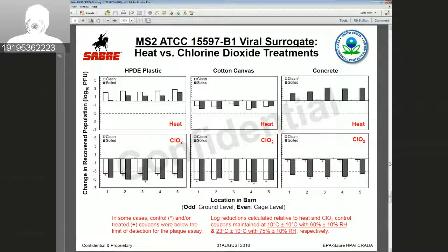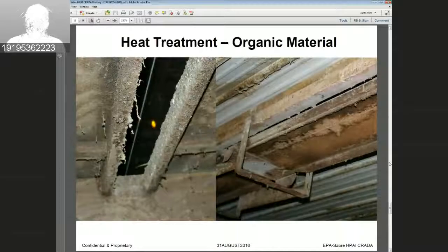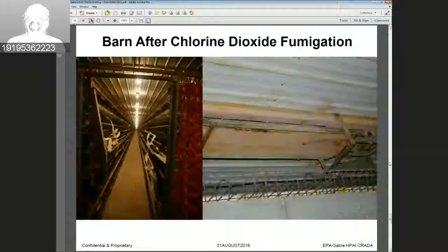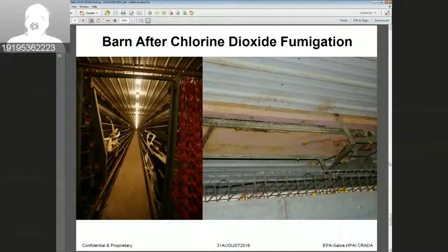The next slide shows the organic material that was present in both barns. It wasn't just the heat treatment barn. There was a little bit of crud you can see hanging on. They've been cleaned very well, but there still was a little bit of organic material hanging off of these barns. These barns were roughly 25 years old, so there was a little bit of damage and corrosion in each of these barns before we even started. Next slide shows the barn after chlorine dioxide fumigation. One of the things that was noticeable was the bleaching effect of the chlorine dioxide on the surfaces in there.